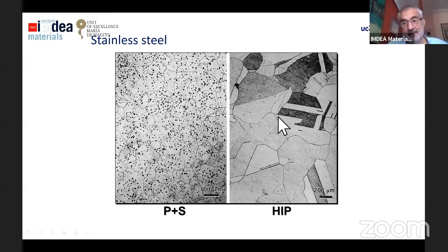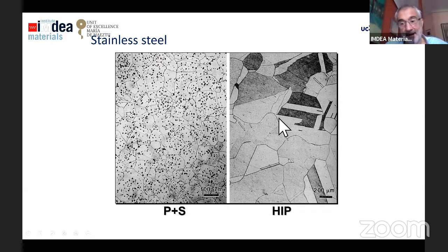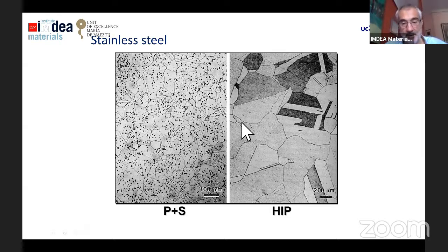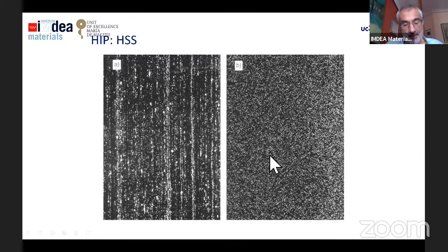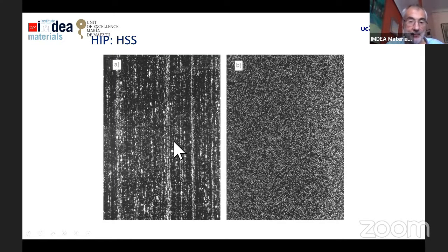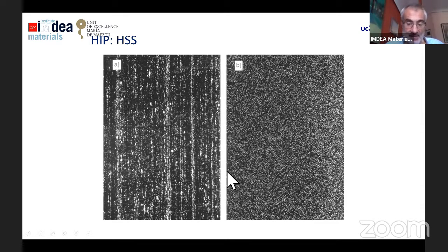Here we have examples of metallic materials produced by hot isostatic pressing — a maraging steel for outer space. A typical comparison between press-sintering and hot isostatic pressing shows that in HIP you have no porosity — fully dense material — compared to conventional press-sinter stainless steel. However, grain size grows considerably because the porosity that normally helps avoid grain growth is absent, and the long cycle time promotes grain growth. A typical application for HIP is high speed steels, which reach full density with a very good distribution of carbides, superior to conventionally forged material which shows coarser carbides with directionality in the forging direction.